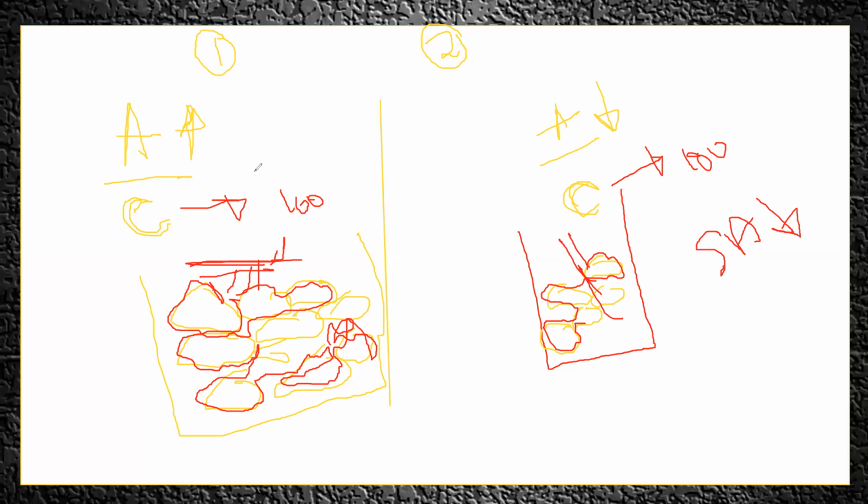It's very simple. Let us say I've taken 100 kg of cement paste in both cases. Here, out of 100 kg, let us say 80 kg of the cement paste has gone in covering the surface area. Only 20 kg of the cement paste is left for the lubrication. But in case 2, since the surface area of the aggregate is less, because fewer aggregates are there, let us say only 50 kg of the cement paste has gone in covering the surface area of the aggregate. So how much is left out of 100? Another 50 is left. That means 50 kg of cement paste is left here for the lubrication. That means more workability is achieved compared to the first case.